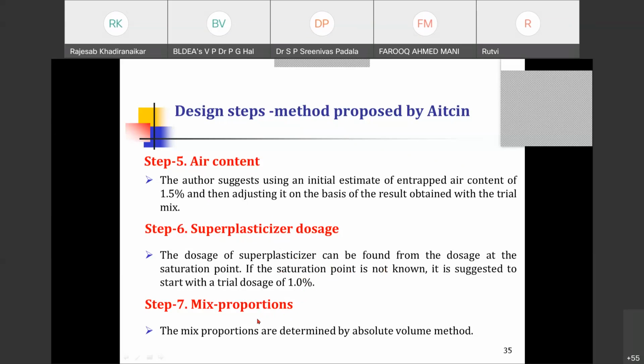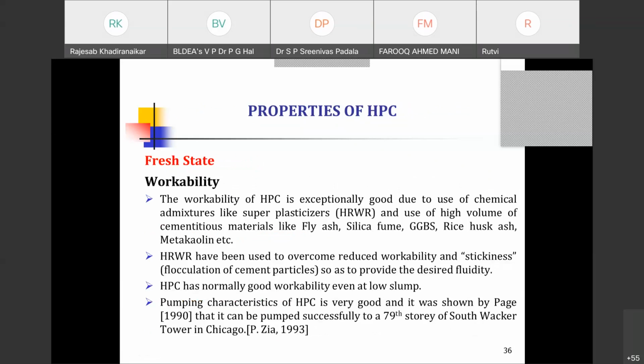Then the final mix proportions are determined by the absolute volume method. Of course, all the techniques use the absolute volume method only. So using absolute volume, whatever other constituent materials are there, you can use that. And if you still want to refine it, sometimes people also go for, particularly when it comes to the superplasticizer, separating the liquid content in that, and then the liquid content as well as the solid content. That level of refinement you need.